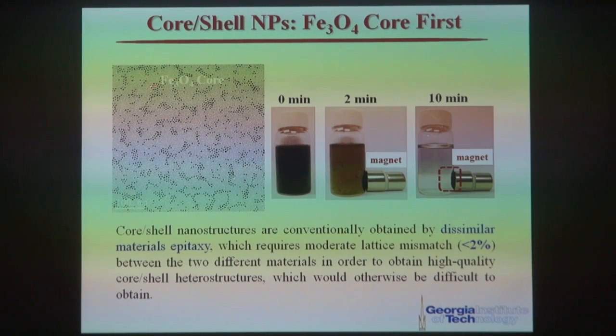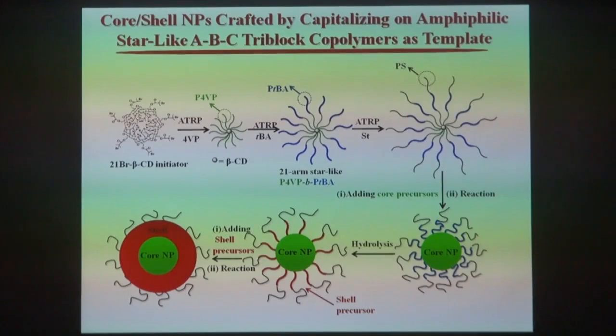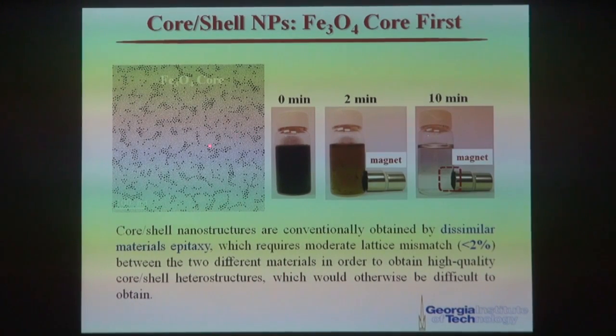So we made the magnetic iron oxide core first by reacting magnetic iron oxide precursors with the 4-vinylpyridine group in this tri-block polymer, forming the magnetic iron oxide core. As you can see, it is highly magnetically responsive. When you put a magnet next to it, you see all particles get deposited on the wall. So this is the core nanoparticles.